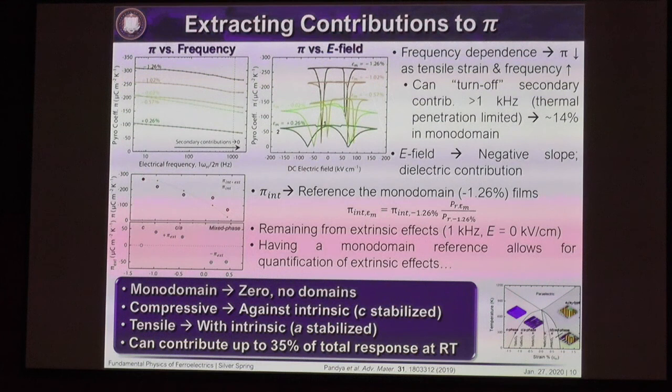And up to about 30-40% of the overall pyroelectric response can come from these domain wall extrinsic contributions in these materials. So if you have these kind of domains, this ability to control the domain structure, you can see interesting evolution of these behaviors.